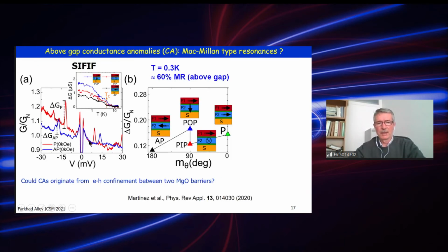Interestingly, we observe a resonance enhancement of the conductance, which is basically a kind of quantum well state formed in the iron, and these states are formed mostly below critical temperature. The amplitude of these resonances, which are a kind of McMillan resonances, depends on the orientation of the iron hard and soft layer—this relative orientation of the soft layer controls the magnitude of the resonance.